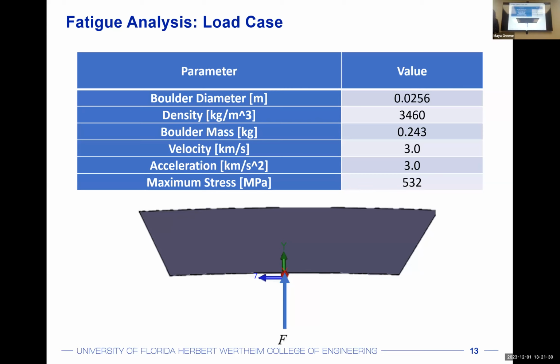Properties of lunar dust regolith were then applied in order to calculate a mass, and then velocity and acceleration that we might expect when impacting the structures was taken from either experimental data on lunar regolith dynamics or information about the Apollo experiments themselves. And this led to a calculated maximum stress in the load case of 532 megapascals. The surface itself was estimated to just simply be a flat plate experiencing cyclic loading. And since the thicknesses of the deflection skirt and the undercarriage dome are consistent and made of the same material, this analysis was deemed as acceptable for both of those structures.